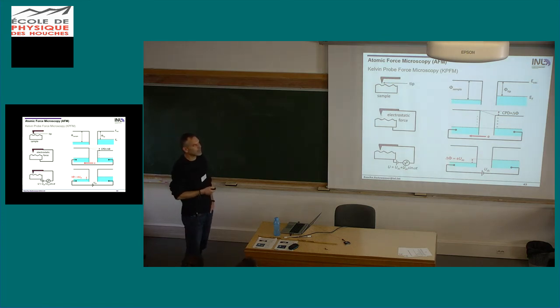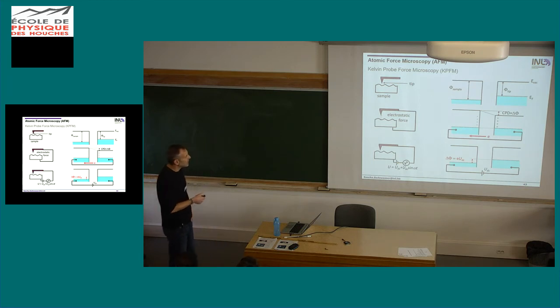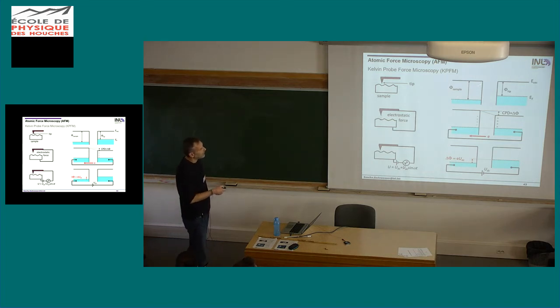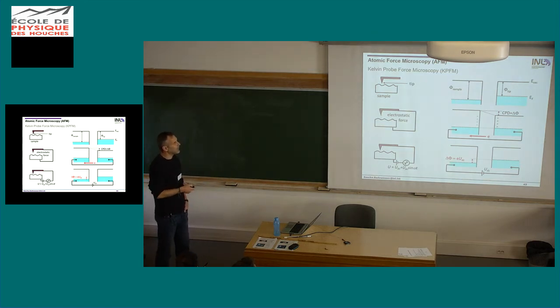So what we measure is electrostatic forces. So it's still the vibrating capacitor method, but we measure electrostatic forces. And the way this works is illustrated on this view graph here. So we can assume the sample and the tip, let's just go for simplicity just to have them both metallic. And if we have these two completely disconnected, then we also saw yesterday that the vacuum levels are aligned, and we have here Fermi-Level in the sample and Fermi-Level in the tip.